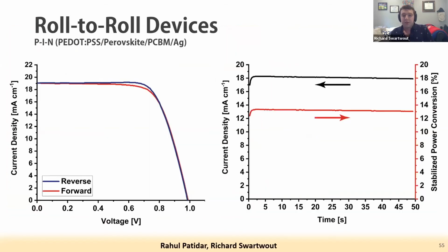In collaboration with Tristan Watson's group and Rahul from Swansea University, we extended this to roll-to-roll based capabilities. Before was obviously our sheet-to-sheet coater. I do want to make a note that this is a change in device architecture, so a PIN-based system, but the champion device here was about 13%, which shows that there is a very easy translation from the small scale devices, which again stabilized about 14, up to this champion device on roll-to-roll for 13.